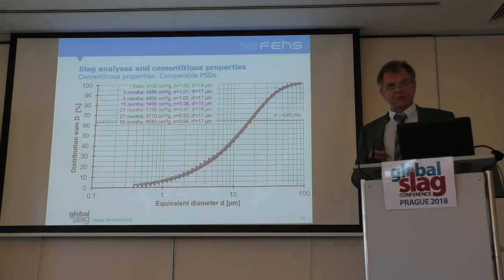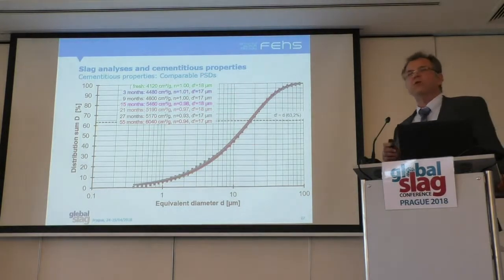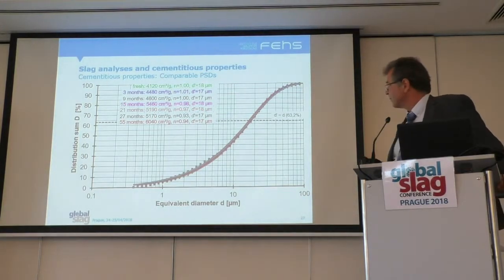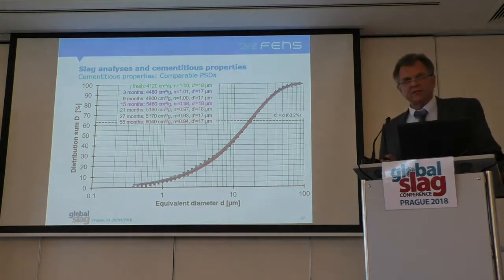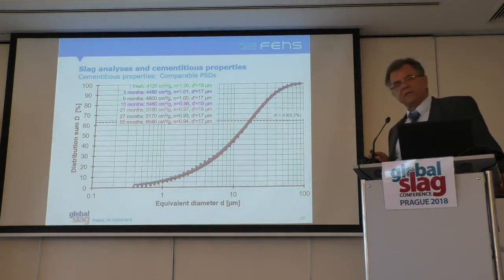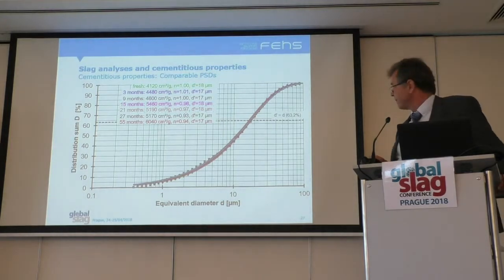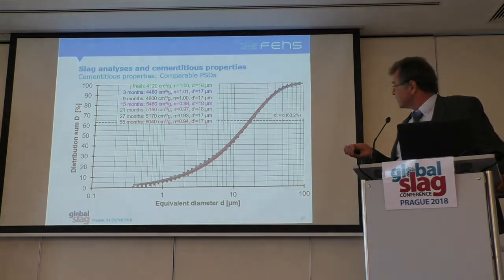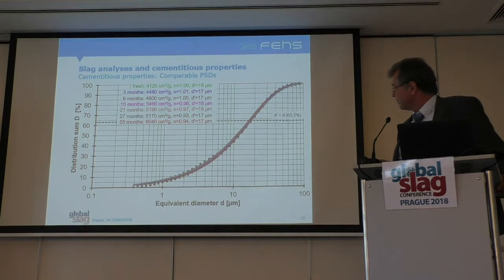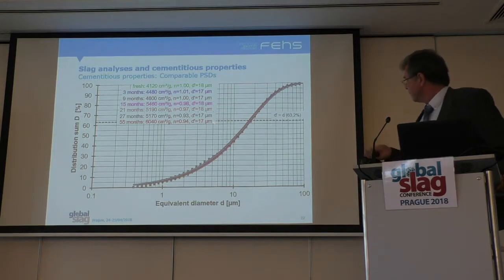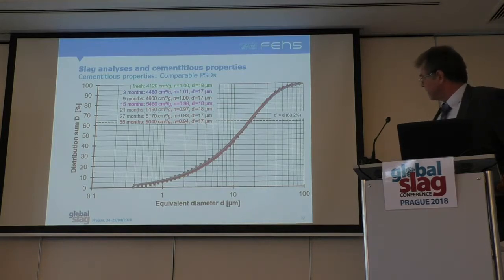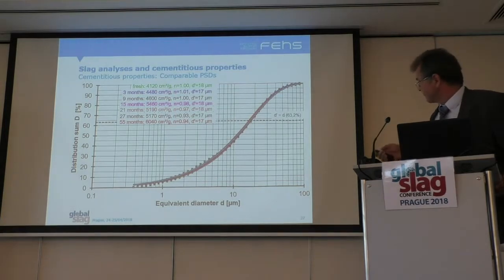Looking to cementitious properties, we always in the Institute try to adjust a comparable particle size distribution. Also in our project here. That's our starting point, fresh slag, about 4,120 Blaine. Green curve somewhere in the middle. And here we see the different values for the stored slags.